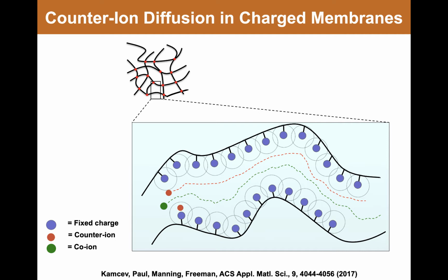However, there is a second population of counterions. There are these counterions that are, in Manning's terminology, condensed or bound to the backbone of the polymer chain. And the question is, can they move? And there's evidence in the literature, from the polyelectrolyte literature, that they can, and that they move primarily along the polymer backbone, rather than moving away from it, although there certainly is an equilibrium exchange between condensed and uncondensed counterions, but they're largely confined to move along this polymer backbone. And so that provides an additional mechanism for counterions to be transported through this membrane.